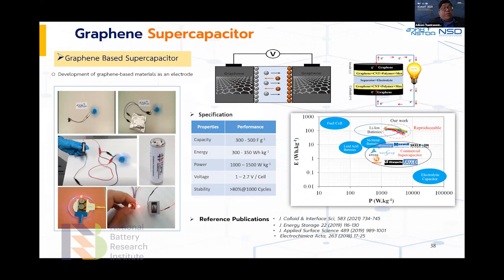In our center, we use graphene in supercapacitors in many forms and applications, such as mixing the graphene into a nanocomposite and making an electrode out of it. For example, nowadays in our labs, we can reach an energy density of about 300 to 350 watt-hour per kilogram, and capacity of about 300 to 500 farad per gram. And if we put it into the Ragone plot compared to other types of energy storage and also to the commercial supercapacitor, we are about here. We have a higher energy density with the same power density.